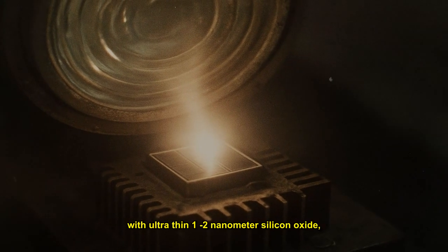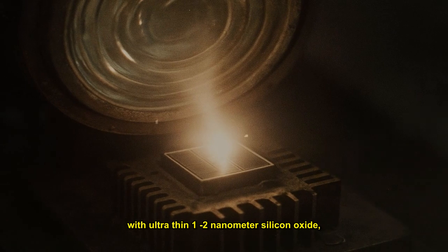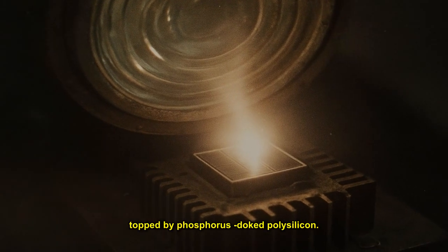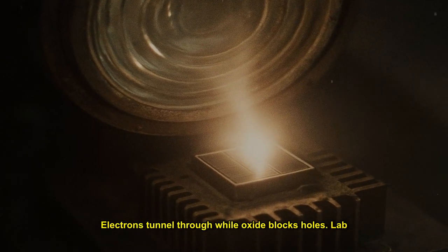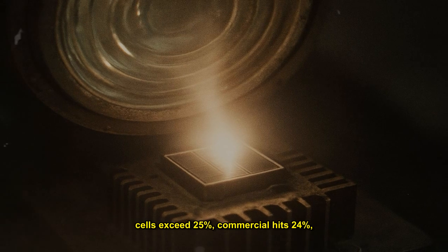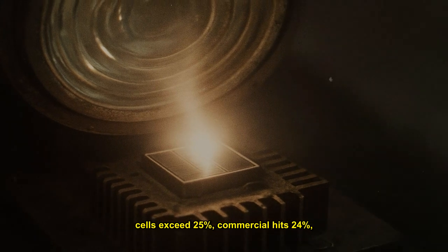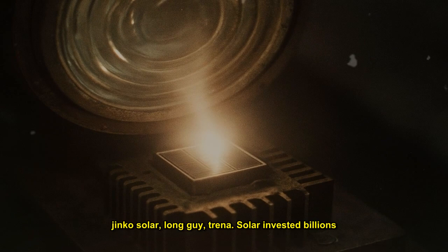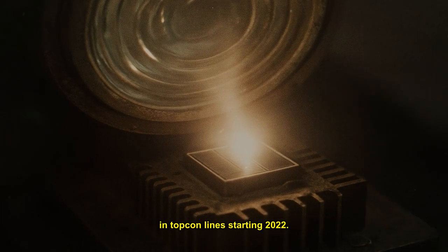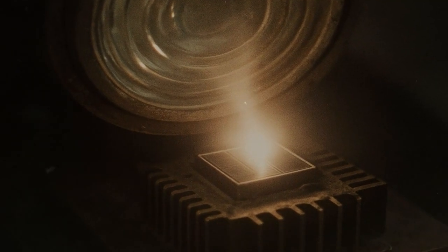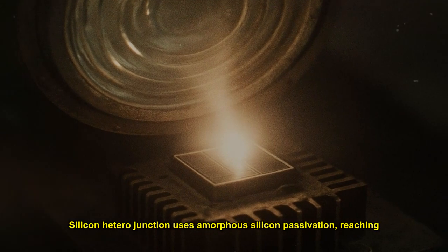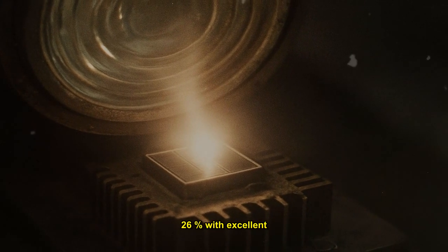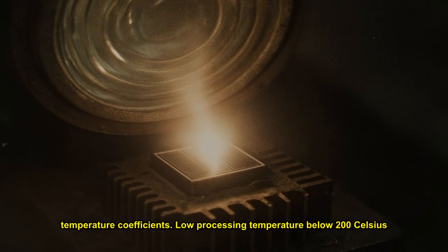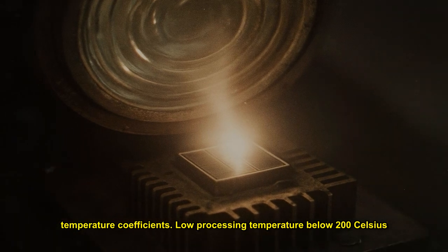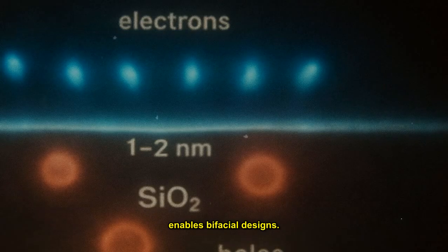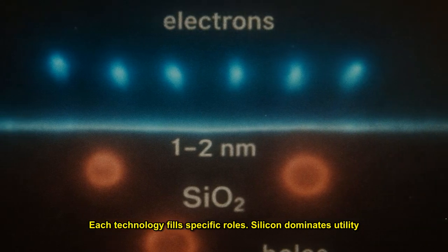TOPCon pushes further with ultra-thin 1 to 2 nanometer silicon oxide topped by phosphorus-doped polysilicon. Electrons tunnel through while oxide blocks holes. Lab cells exceed 25%, commercial hits 24%. Jinko Solar, Longi, Trina Solar invested billions in TOPCon lines starting 2022. Silicon heterojunction uses amorphous silicon passivation, reaching 26% with excellent temperature coefficients. Low processing temperature below 200 Celsius enables bifacial designs. Each technology fills specific roles.